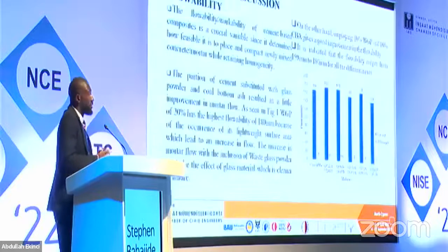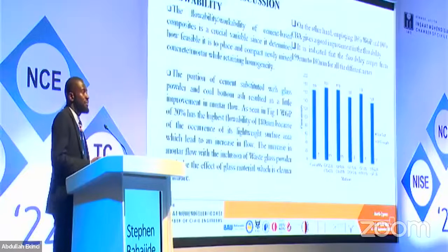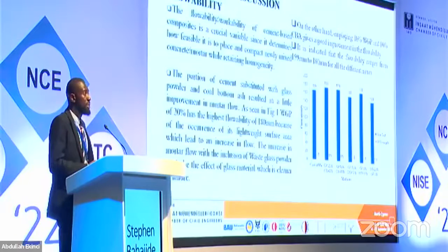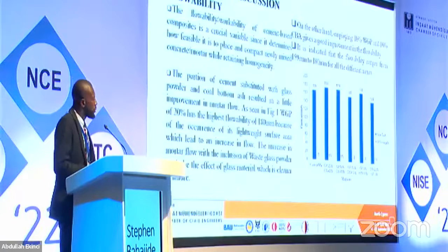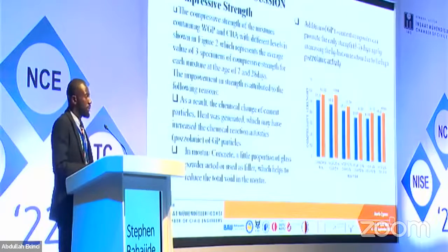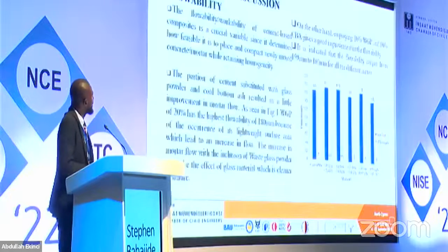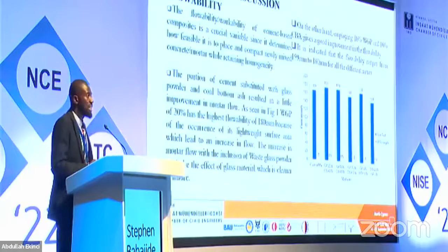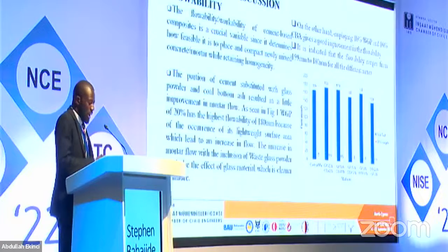My result and discussion. I have different results which are based on the flowability or workability, and also the mechanical properties. I move to my flowability. It is stated that 20% of waste glass powder increases workability, which might be due to the lightweight surface area of glass powder that increases the flow.